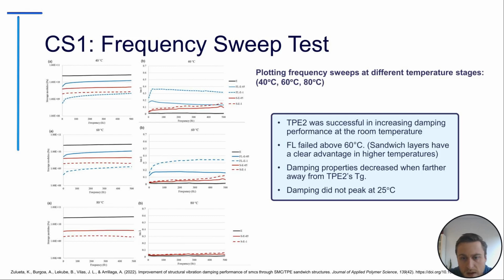I will note too that although the Tg was listed near room temperature, the damping performance did not peak at 25 degrees Celsius. We can see at 40 and 60, there was still very good damping performance, dependent on what configuration was used.